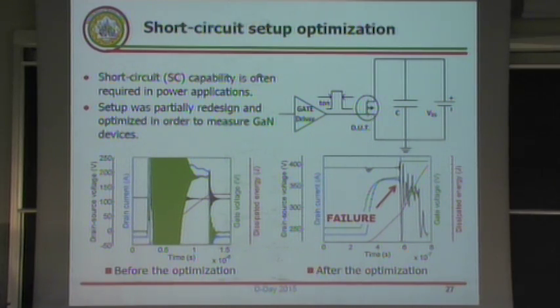And after this optimization process, the waveforms were very nice, and we were able to measure and characterize the short circuit capability. And we obtained very interesting results. We were able to also explain the failure mechanism of these devices. Unfortunately, all the results we have obtained are confidential, so I cannot present them.